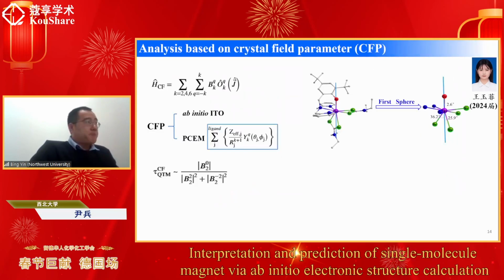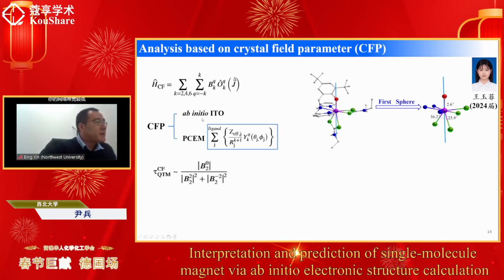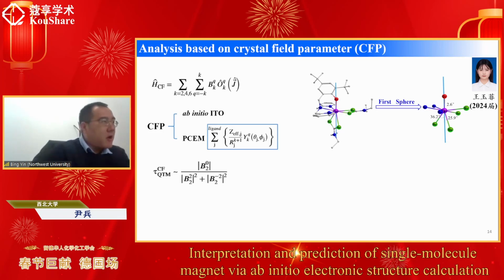And we also did some analysis based on the crystal field. The crystal field is a theoretical model which is popular for lanthanide compounds. And the crystal field Hamiltonian consists of the crystal field parameters B_k^q as well as some Stevens operators O_k^q. So the characteristic of a given lanthanide system is actually determined by the crystal field parameters B_k^q. And these B_k^q, or crystal field parameters, can be extracted from ab initio results based on the ITO, irreducible tensor operator, technique. And they can also be estimated, although not very accurately, by the very simple point charge electrostatic model.